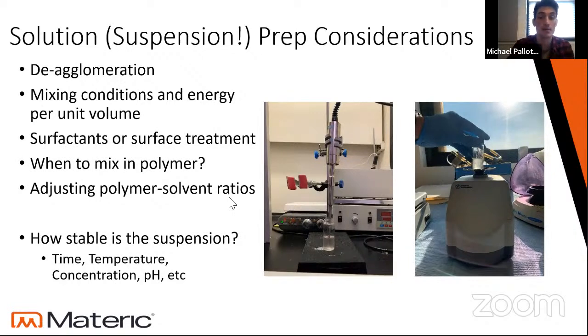When to mix the polymer, this becomes a very empirical process, which took us a number of iterations with some of our projects to find that creating the nanoparticle solution and a polymer solution separately and then adding them minutes later after vortex mixing both, that's what we have in our standard operating procedure for a lot of our projects now. But most of that comes from mixing the polymer solution and the nanoparticles and then spinning